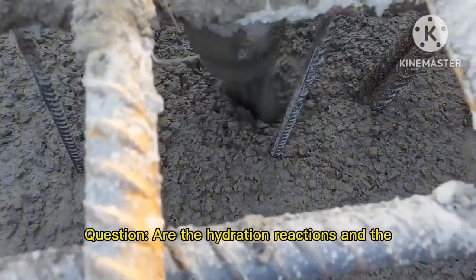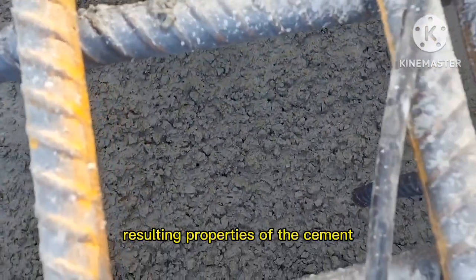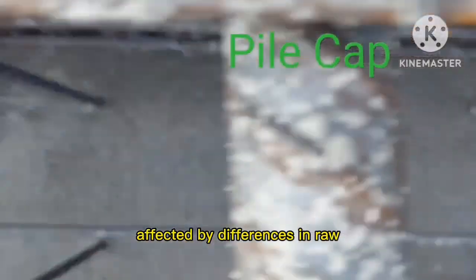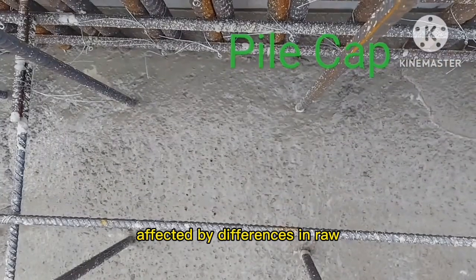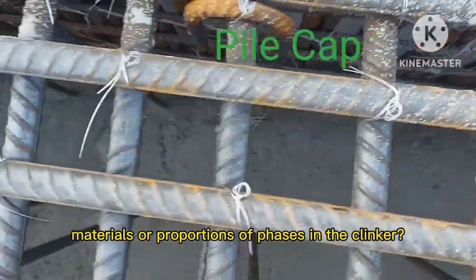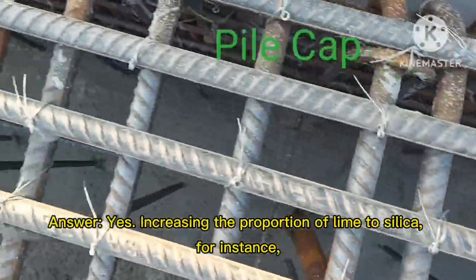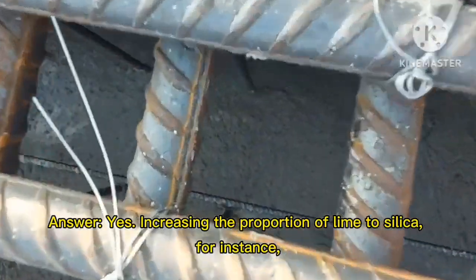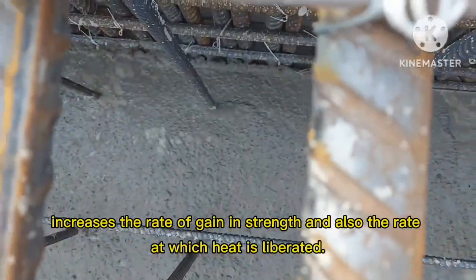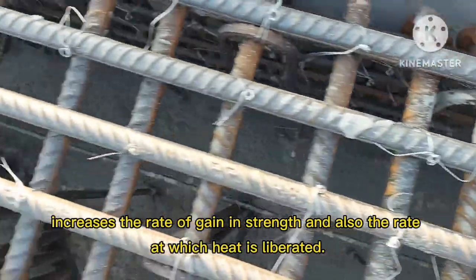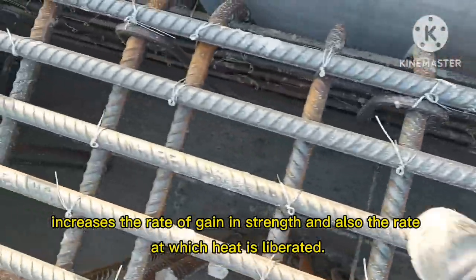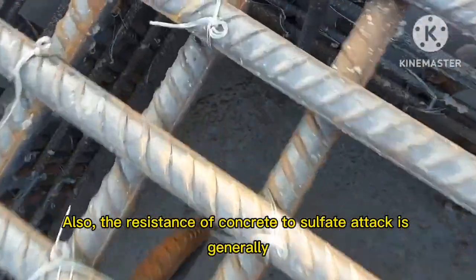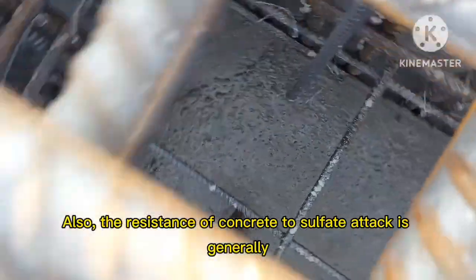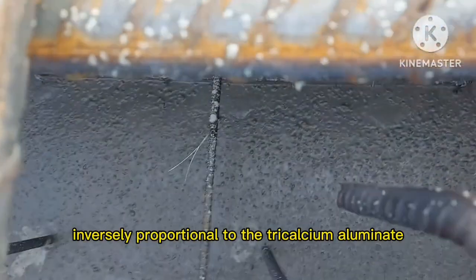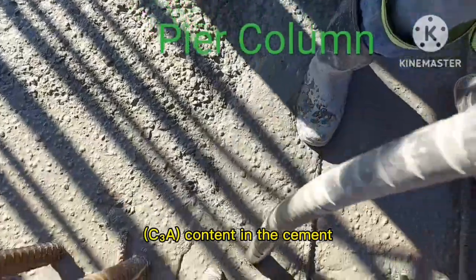Question: are the hydration reactions and the resulting properties of the cement affected by differences in raw materials or proportions of phases in the clinker? Answer: yes. Increasing the proportion of lime to silica, for instance, increases the rate of gain in strength and also the rate at which heat is liberated. Also, the resistance of concrete to sulfate attack is generally inversely proportional to the tricalcium aluminate (C₃A) content in the